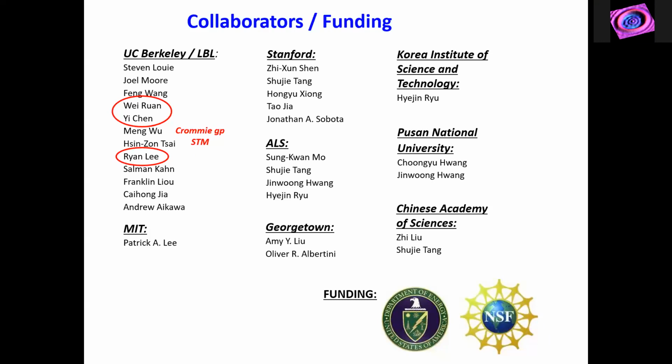That's a good question. Experimentally, we can put some limits on the J. We think that the J coupling between those local moments is not so strong because the Kondo effect can overcome it, and the Kondo has a Kondo temperature of 60 Kelvin. We're emphasizing that the spin is coming from the central atom of the Star of David, but actually, this is not a single band Mott insulator. It's a multi-band picture because we really have the whole Star of David, and so there's still going to be some components of those peripheral atoms.